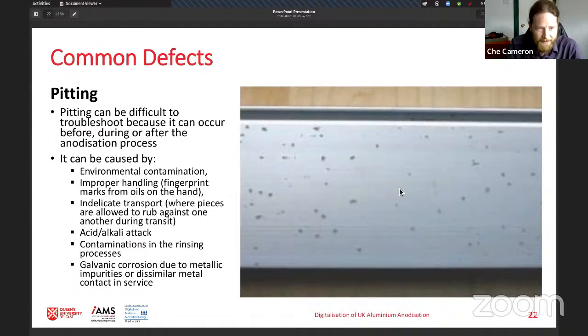So the first one would be pitting. And this is not necessarily the fault of anodization, nor is it unique to anodization, but it's nevertheless a common problem with metal finishes. And it's usually caused by a contamination of some sort. It could be oils or acid or alkali attack, and can be galvanic corrosion sometimes. So this is a lot about design, logistics, transport, and looking after the metal if you want to avoid this. There's not much you can do, but anodization will tend to make this underlying problem much more visible once it's been applied.